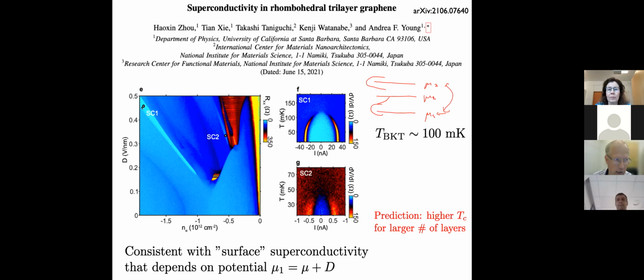Yes, they can vary one mu at a time, and what they see is, basically what is done on the left here, and they show the resistance or resistivity as a function of these two parameters. So this is proportional to the total mu, and my claim is that in order for this to be valid, this depends only on this mu plus minus d. You have to have this kind of dependence, that it depends only on the sum or difference. Okay, and I think this is consistent with that. But that's the only thing that I can state at the moment about it.